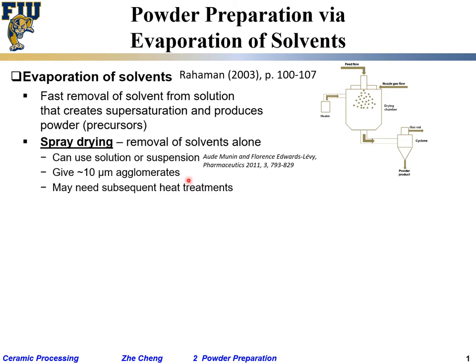In this way we get reasonably uniform spherical particles or agglomerates. The cooled gas exits and the powder is collected in a container. This is called spray drying. Quite often you get around 10 micron agglomerates, which people use for many different applications — the powder flows very nicely.